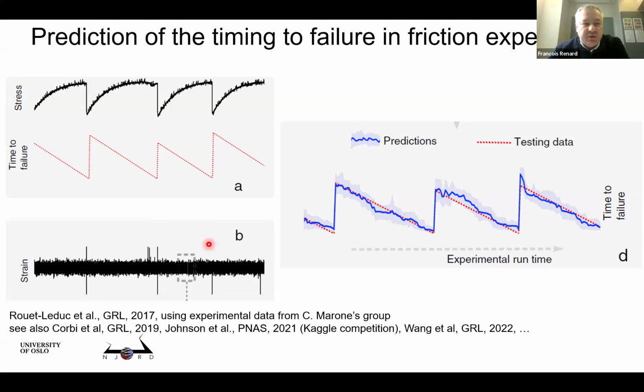So there were more and more papers on this topic, where the idea is to use stick-slip experiments where the shear stress is measured as a function of time. And each stress drop here corresponds to an earthquake, a laboratory earthquake. And in this experiment also, the acoustic emissions are recorded. So that's the acoustic emission. And the idea of all this machine learning approach is that if we know this curve at every point, because the horizontal axis is time, we can predict what is the time to failure. So 0 means the point here, there is an earthquake. Then the time to failure increases, and then it will decrease again through this linear step function.